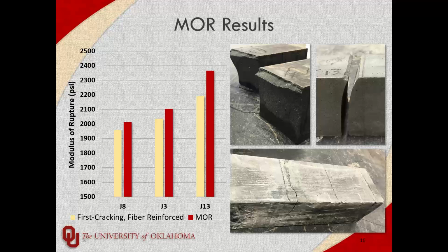But the unreinforced modulus of rupture tests, every single one of them had this really interesting failure crack, in that it started vertical at the bottom, where the highest flexural tension stress is going to be, and then as it reached up, they all had a slight curve to about 1/8 of an inch from the top of the specimen, and then a jog back, which we're still not sure what it indicated. It's something that I personally would like to study more, because it looks more like a tearing motion than a typical concrete cracking motion. So it could indicate a potential for increased energy absorption capabilities. We're not sure. Like I said, I'd really like to study it later, but we've had other more pressing projects to work on. Next slide.